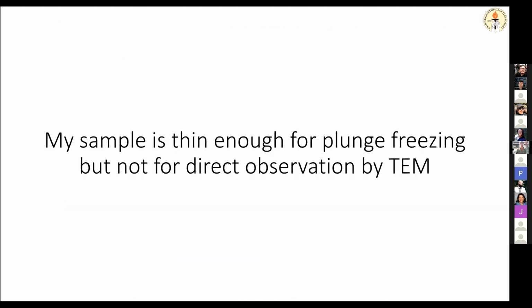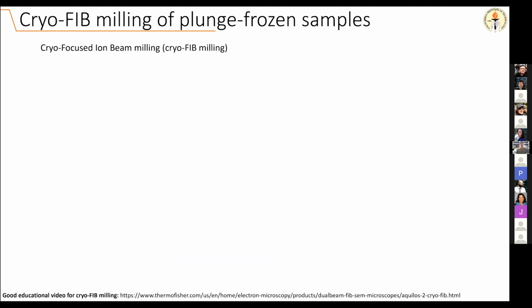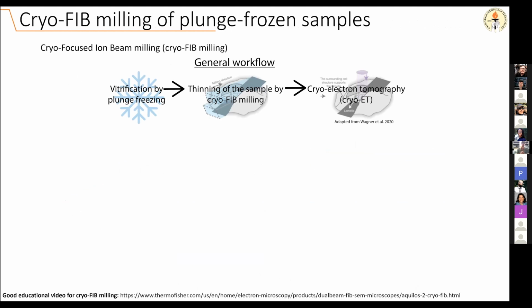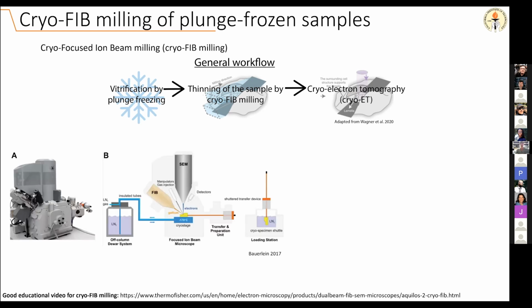So here the first case is my sample is thin enough for plunge freezing, but it's not for direct observation. So we're observing something that's in the ranges of a few microns in thickness. So the general workflow here is that we are going to plunge freeze our sample the same way Lisa described it. We're going to thin our sample by using cryo-focused ion beam milling, and then we're going to transfer this grid in the Cryo-TEM, and we'll acquire data on the thinned lamellae.